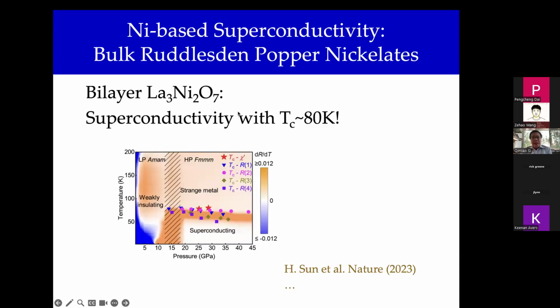The more recent discovery was on the bilayer nickelates, 327. This is in the Ruddlesden-Popper series, and Tc under pressure reaches on the order of 80 Kelvin, and there are a number of other features in this phase diagram. There are some changes of different kinds, going from a weakly insulating regime to a metallic regime in the normal state. Initially, there was a considerable challenge with the materials, and there was some discussion about whether even zero resistivity had been achieved, or what the volume fraction was, and all that.